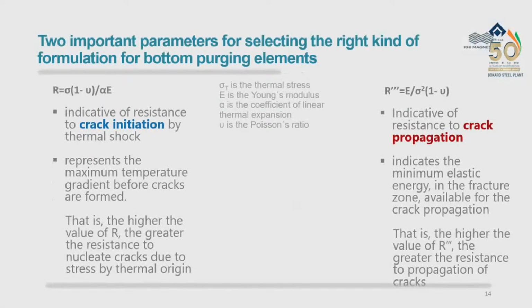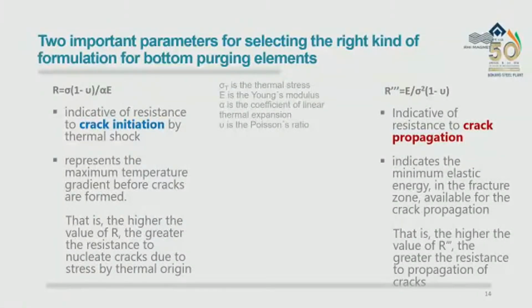So basically, we talk about these two types of resistance. One is R and one is R triple dash. This is basically a crack nucleation resistance. The crack is initiated. It represents the maximum temperature gradient before it's formed. So basically, this is expressed in degree centigrade or degree Kelvin. So the higher the value of R, the greater the resistance to nucleate cracks due to stress of thermal origin.